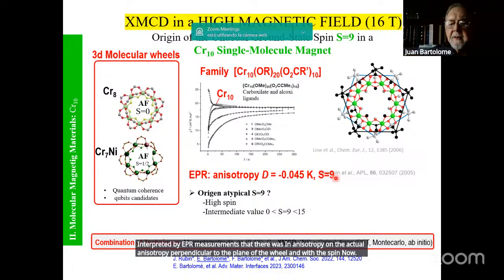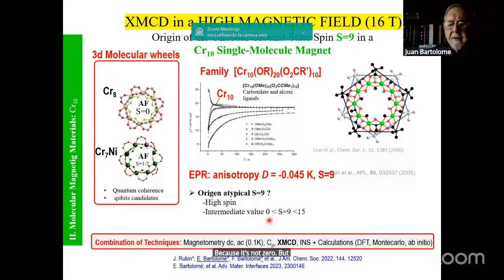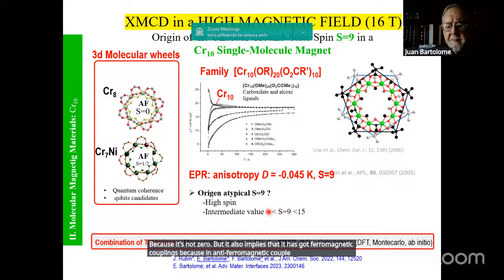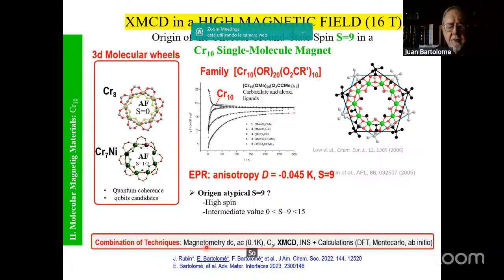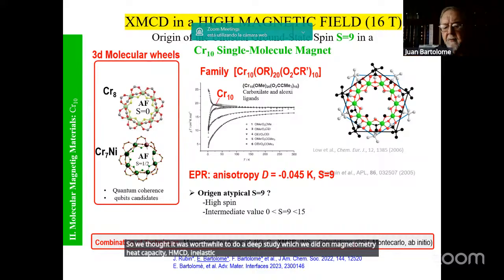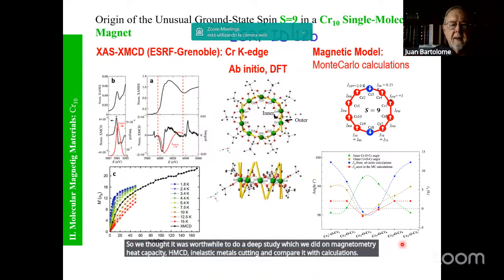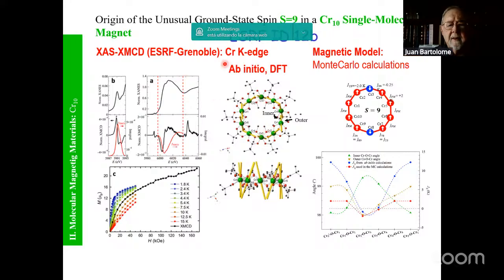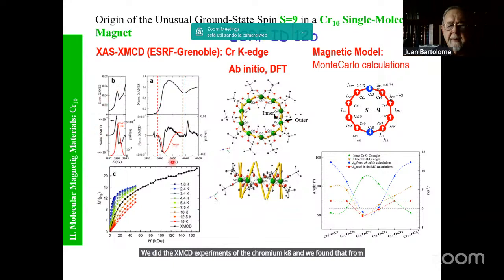This spin 9 is very interesting because it's not zero, but it also implies that it has ferromagnetic couplings, because antiferromagnetic couplings would give us a spin 0. Totally ferromagnetic coupling would give us spin 15. So we thought it was worthwhile to do a deep study, which we did with magnetometry, heat capacity, XMCD, inelastic neutron scattering, and compared it with calculations. We did the XMCD experiments at the chromium K edge, and we found that from that point of view, all chromiums were identical.